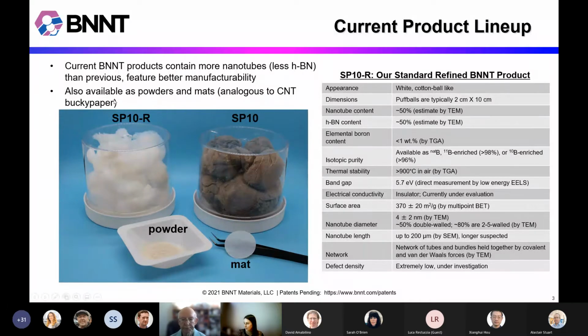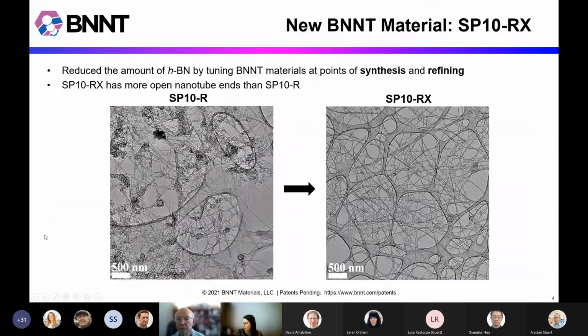We can also process this material into various form factors: dispersions, powders, or what we call mats, which are the BNNT analog of a carbon nanotube bucky paper. What we've been working on in the last year or so is to further purify our standard product to remove that hexagonal boron nitride. You can see a couple of TEM micrographs here, with the nanoscale bits of hexagonal boron nitride that we're trying to remove to generate what we're calling SP10RX, which is a highly refined material that is more nanotube rich.